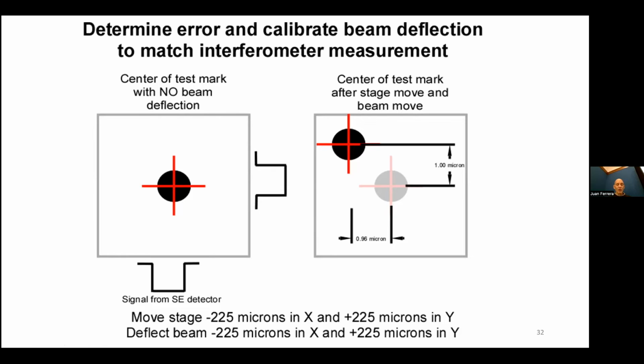And then we tell the stage to move. In this case, I'm saying 225 microns in X and 225 microns in Y. And we also tell the beam to move that far. So we move the stage and we move the beam. If everything was perfectly calibrated to each other, our circle would be right back here in the middle, but it won't be because there's drift with time. Instead it shows up over here. We measure the distance in between these two things, and then we recalibrate the deflection of the beam deflectors that tell the beam where it's going to land.